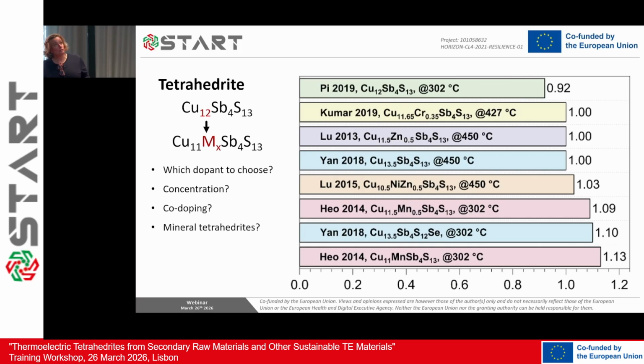If you go to the literature, it's very confusing, because everybody does a study. They may even choose several compositions of the same elements, but then when they report it, they report the maximum ZT, which is never at the same temperature. So you don't really understand - if the undoped case was measured at 302, maybe at 427 it's better than this one, so maybe you should not have doped. It's very difficult to understand what should we do with the compositions.